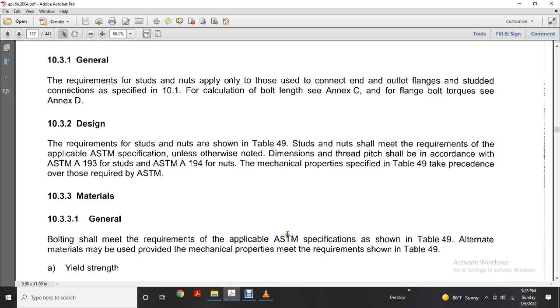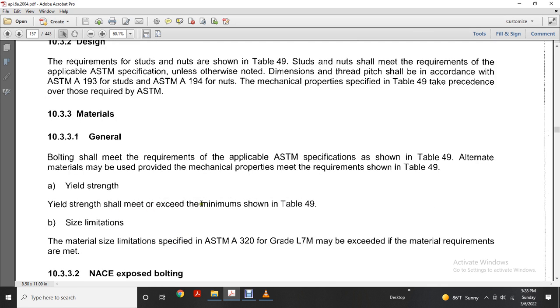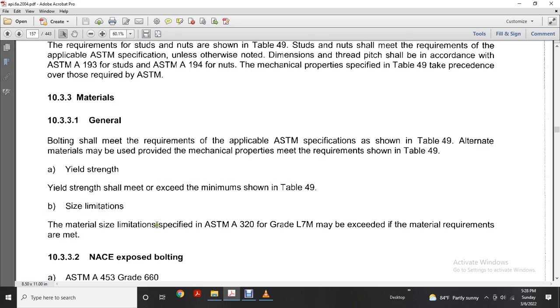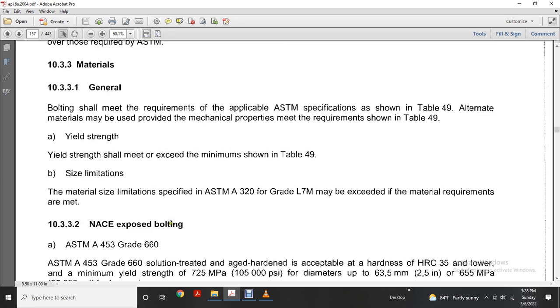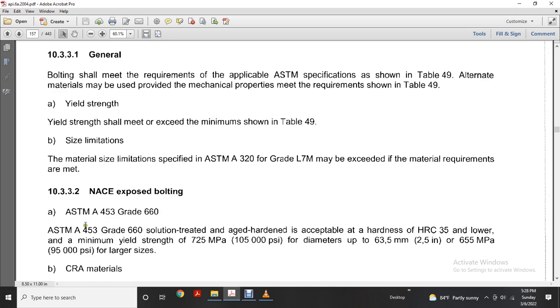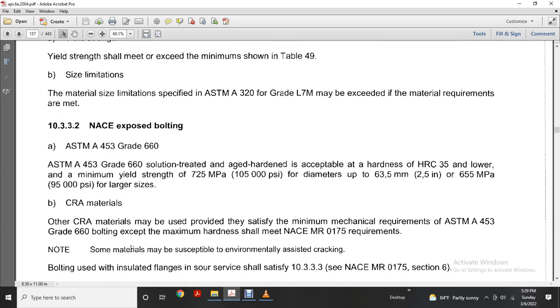Materials. General bolting shall meet the requirements of the ASTM specification shown in table 49. Alternate materials used shall provide the mechanical property requirements shown in table 49. Yield strength shall meet or exceed the minimum limits shown in table 49. Size limitation: material size limitation for ASTM A320 grade L7M may be exceeded if material requirements are met. NACE exposed bolting: ASTM A453 grade 660, solution treated and age hardened, is applicable with hardness of HRC 35 or lower and a minimum yield strength of 105,000 PSI for diameters up to 2.5 inches and 95,000 PSI for larger sizes. Corrosion-resistant alloy materials: other corrosion-resistant alloy materials may be used if they satisfy the minimum mechanical requirements of ASTM A453 grade 660 bolting and maximum hardness shall meet the NACE MR0175 requirement.